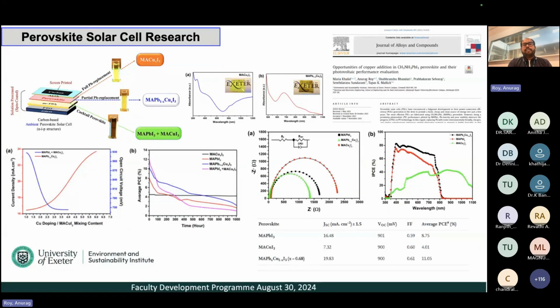Another one, in terms of perovskite materials, a common one is MAPbI3. As I mentioned, lead is toxic, so it is recommended not to use lead, but we can't get rid of lead so quickly because the property of lead is not replaceable by any other metal. But still, we tried with some copper. So we replaced lead with copper, and we tried copper replacement in various ratios. And here you can see how the copper replacement makes an impact when the perovskite structure shifts from lead based to lead copper based to only copper based.